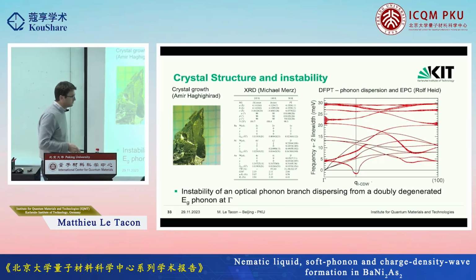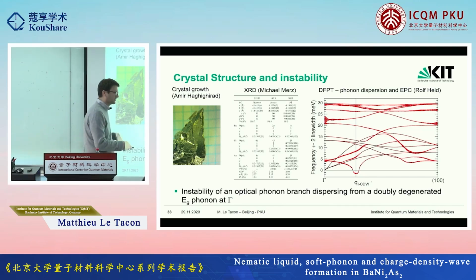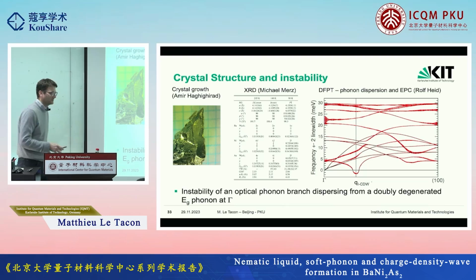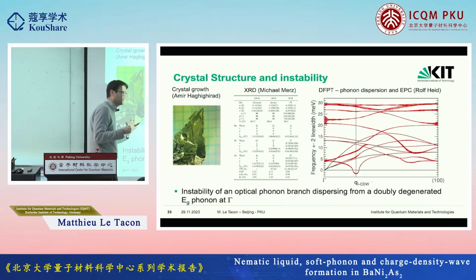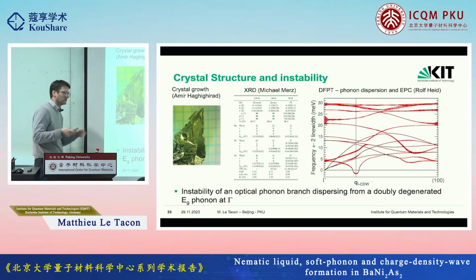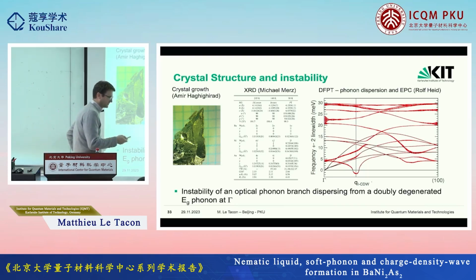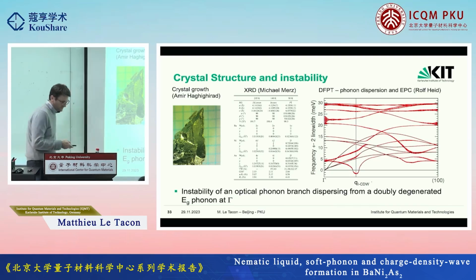I would just like to point out here that we, of course, asked Rolf at the beginning to check what kind of distortion it would take for him to see a lift of degeneracy of the phonon here of the order of 3 millielectron volt, as we see in the experiment. And that's basically impossible for him. He can never get there. There's no way. The kind of strain he has to apply on the structure is of the order of 10% or more, which doesn't make any sense.